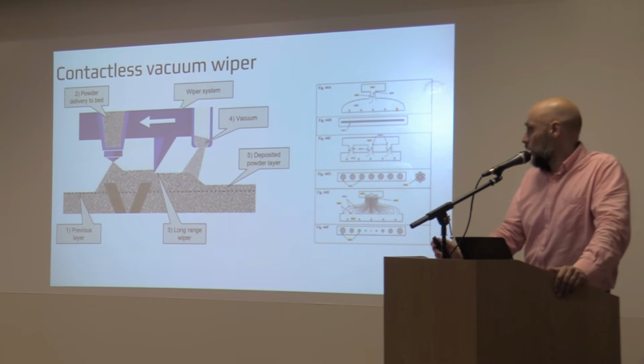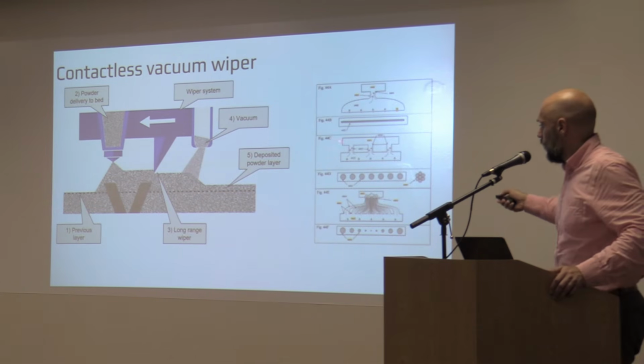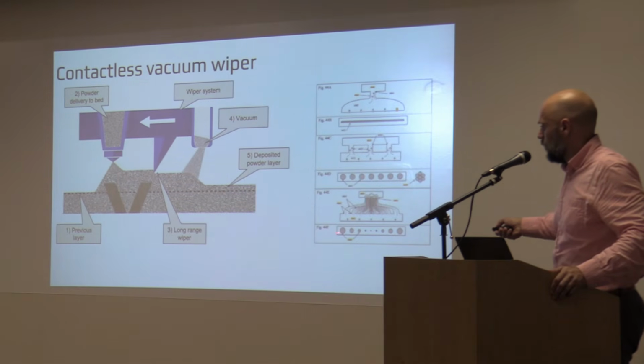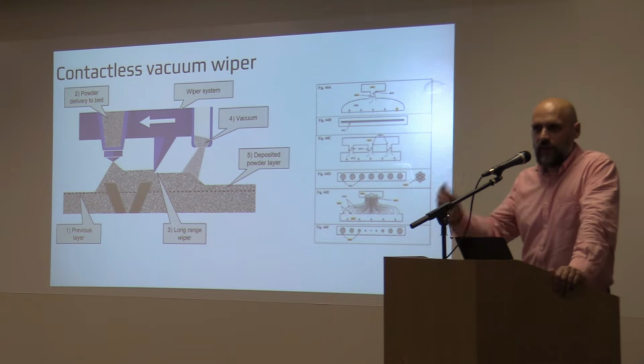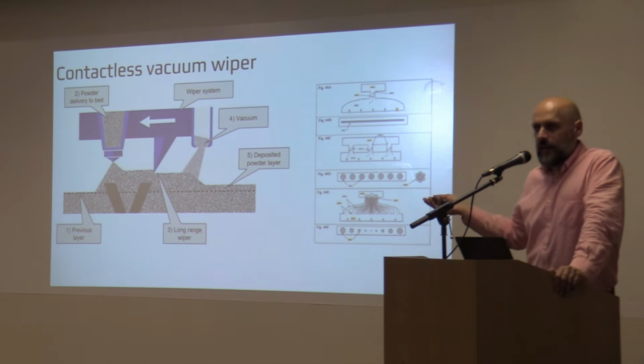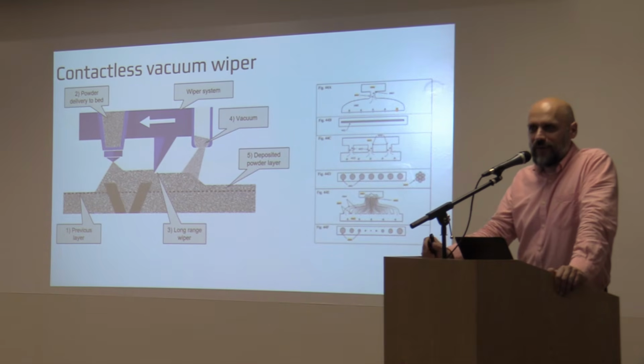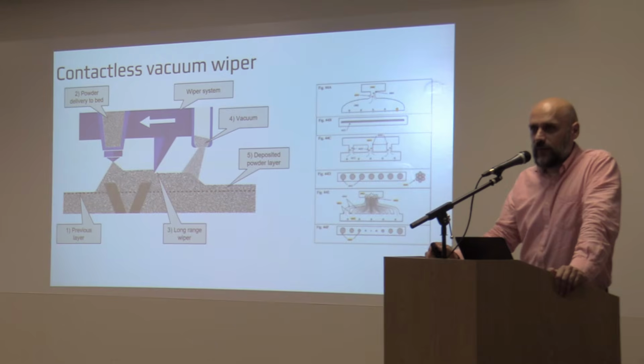And that took a lot of tuning. Here you can see all the patterns of the different layouts. With small holes in the middle, we had high suction; with bigger holes here, we had a linear one. We tried many methods to have a uniform vacuum line. But that's how we did it, and we didn't touch the parts in the powder. So that was the first big innovation here.